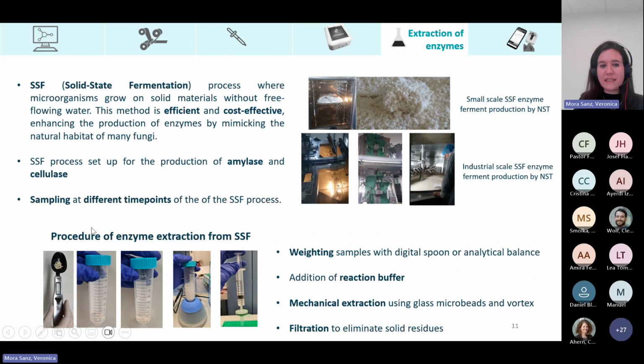So here we can see a very simple procedure that we set up to extract the enzymes from the samples in the fermentation plant. We first weigh the samples employing a digital spoon or an analytical balance. Then we add the reaction buffer, and we perform a mechanical extraction using glass microbeads and by shaking with a vortex. And finally, we eliminate the solid residues by filtration.